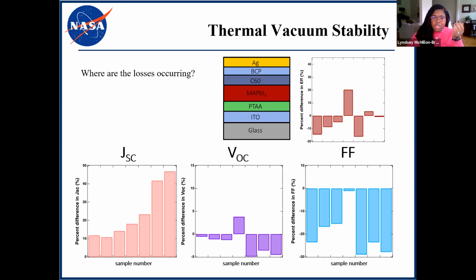And again, we're seeing largely our short circuit current remained unaffected or even marginally enhanced. Our open circuit voltage drops slightly, but really the killer is our fill factor. And from this, we can conclude that thermal vacuum stress is damaging the transport layers. And as a result, we're introducing internal resistance into the cell.